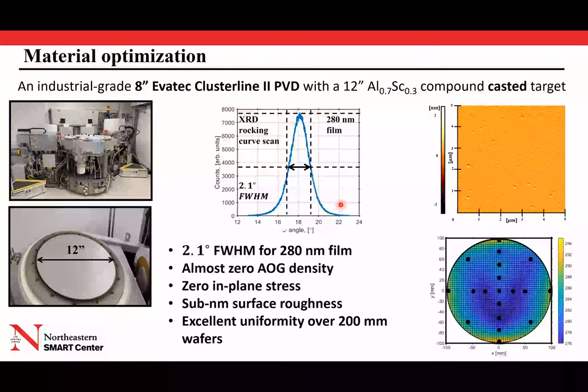So, let me very quickly go through some of the material work that we did. Here you see we used an Evatec Clusterline tool. It's an 8-inch Clusterline PVD system that we have at Northeastern. We use a 12-inch cast scandium aluminum nitride target. So this is aluminum scandium nitride, 30% scandium doping, to deposit on 200 millimeter wafers with very high thickness uniformity. As you can see here, we really optimized material deposition for thin film materials like 280 nanometers that can be used for those high frequencies that I described before.